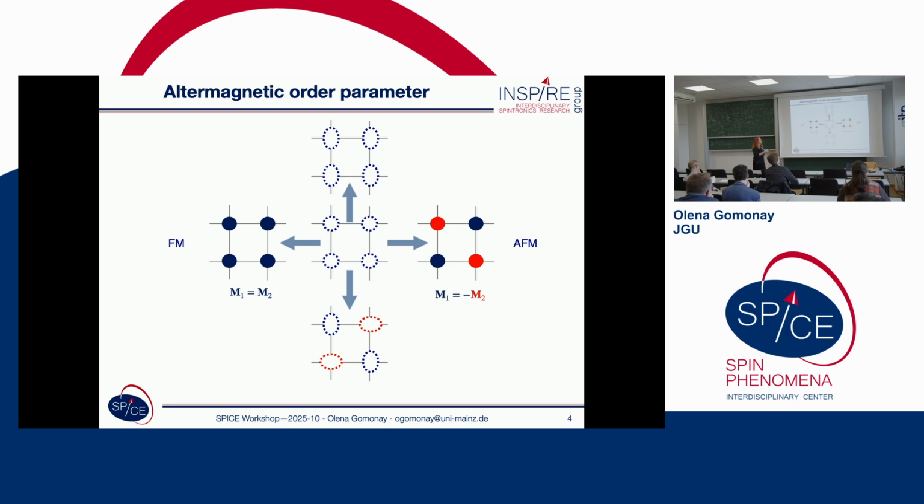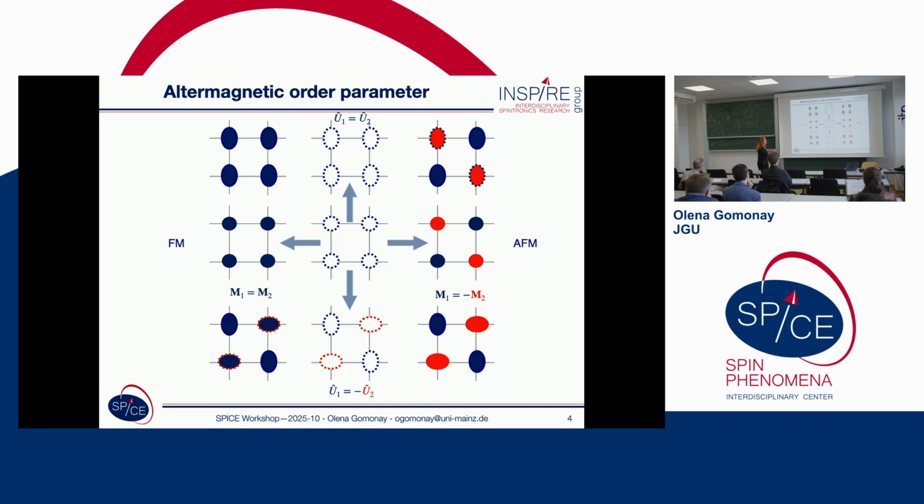We can describe this with the aid of some spherical functions or tensors, but what is important, we introduce these tensors at each site of the future magnetic lattice. In this way we can get a kind of ferromagnetic-altermagnetic ordering, or antiferromagnetic-altermagnetic ordering, but in this line the lattice is still non-magnetic. Then we can imagine that we have a transition to the magnetically ordered state, and then we can get a bunch of different structures.